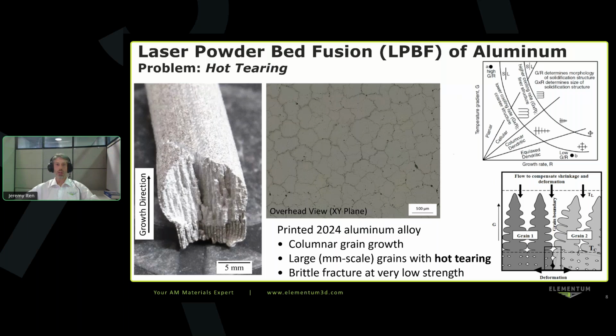Looking at laser powder bed fusion of aluminum alloys, there's a big problem with hot tearing. This is a solidification cracking that happens because of the microstructural growth that happens during solidification. You get very columnar and dendritic microstructure that forms, and in between those columns, you have inadequate backfill of the liquid phase that leads to cracking between those very large columns. You can see that part on the left. The columns are visible on a macroscopic scale. They're millimeter type scale columnar growth that takes place with cracking between those.